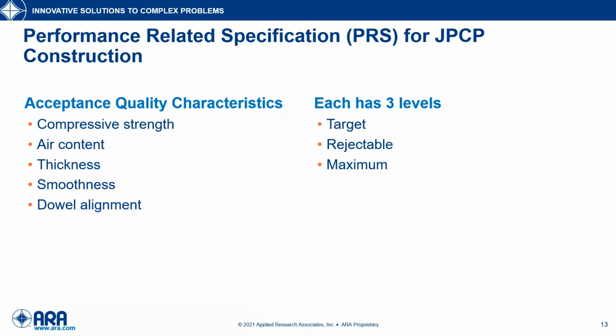So the target quality represents the as-designed pavement quality, and it's the quality level where the contractor would receive 100% pay. The rejectable level represents the minimum quality that can be accepted before corrective action or retesting, reduced payments, or removal would apply. And then finally, the maximum quality level represents the level where no further incentive is achievable. And any pavement that is above the maximum quality level was paid at the maximum incentive.